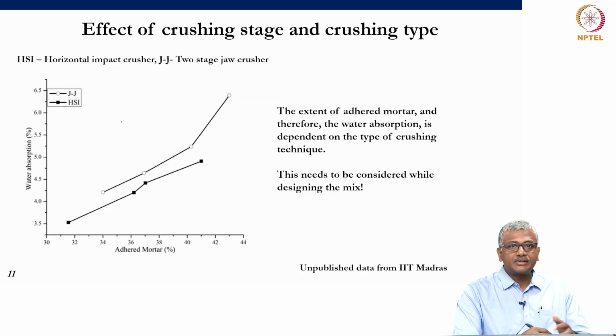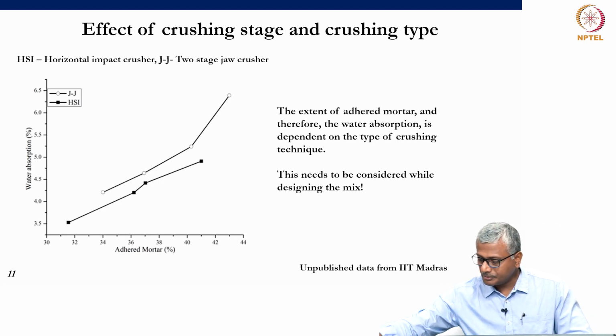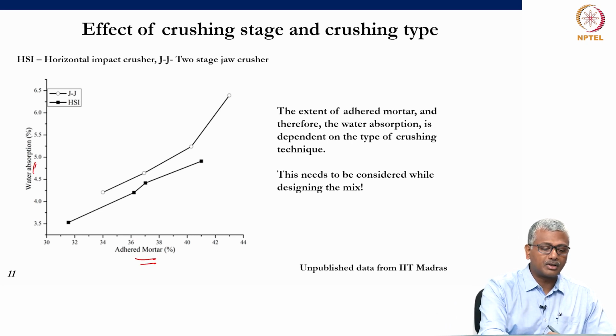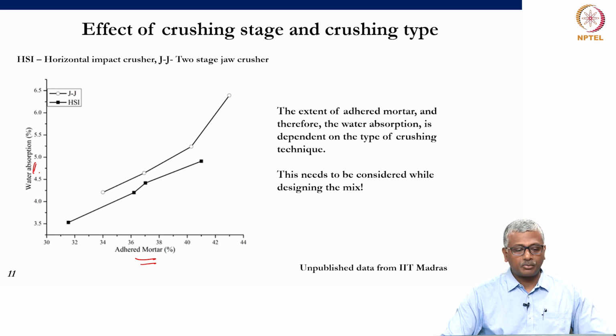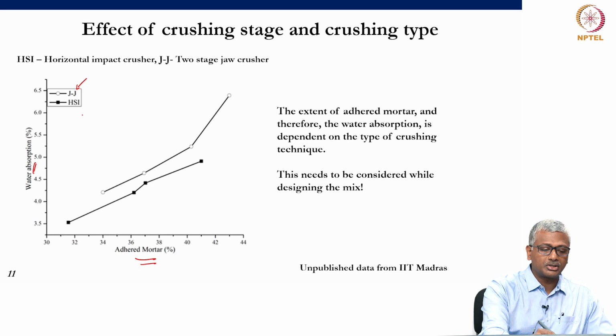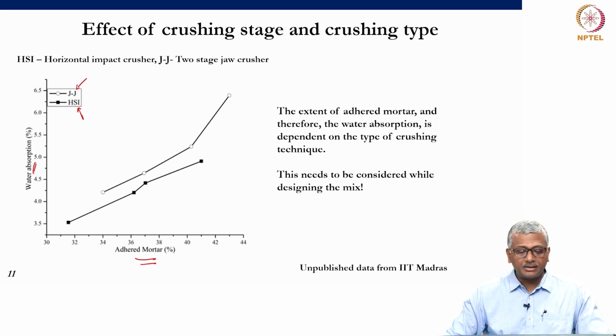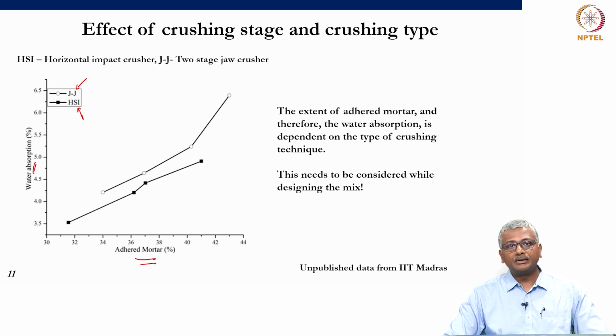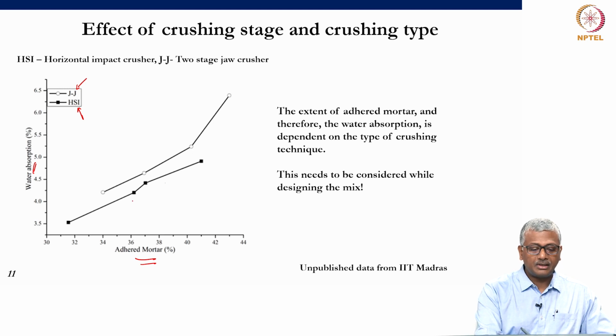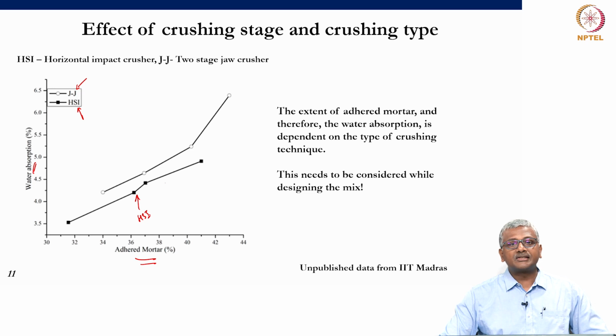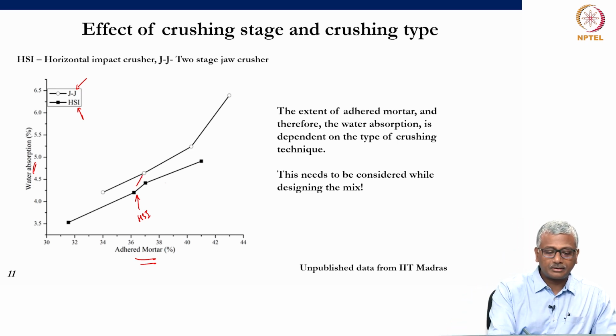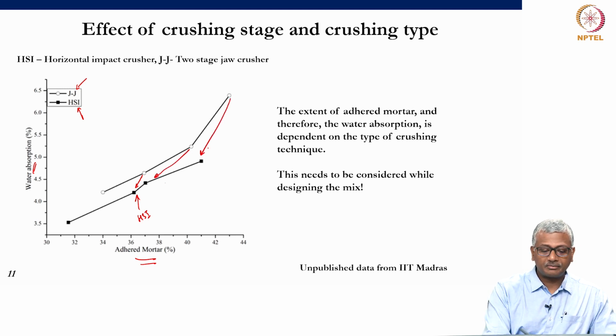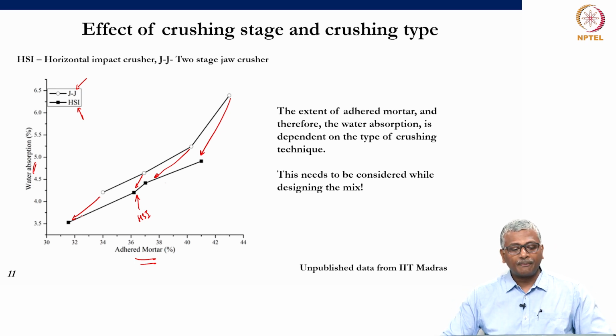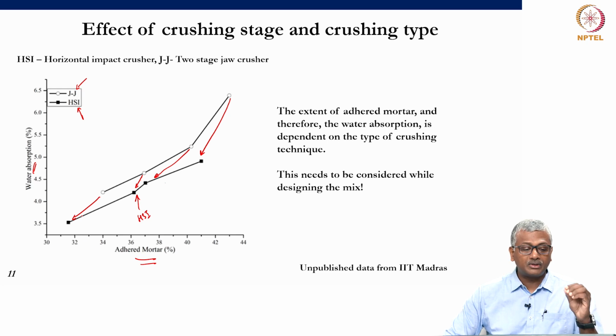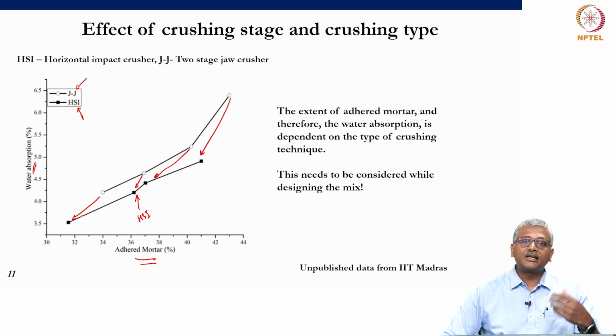So, if you look at some data on what happens to the extent of adhered mortar and the water absorption as a result of adopting different crushing processes. Here 2 examples are given. One is a 2-stage jaw crusher and one is a horizontal impact crusher. What you tend to see here is that the extent of adhered mortar, right, is lower for the systems with the HSI crusher. Okay, the extent of adhered mortar is lower, and for each one of these data points, basically the extent of the adhered mortar is much lower for the aggregate that is prepared with the horizontal shaft impact crushing. And since adhered mortar directly affects water absorption, the net water absorption for such aggregate is also lower.